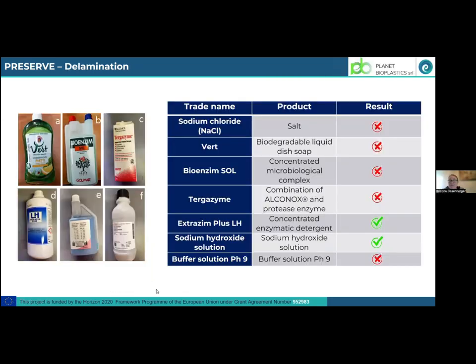Our partners from Bioplastics investigated the delamination potential using enzymatic soaps. As you can see, they investigated numerous different soaps and detergents, and in two cases, for Extrazim and sodium hydroxide, the delamination, so the degradation of the protein layer, was successful.